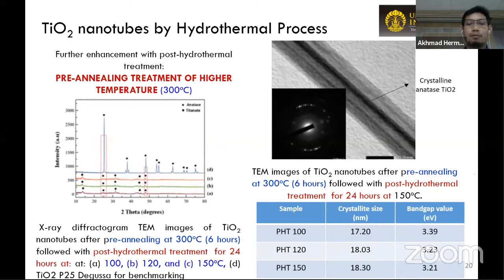From the TEM image we can see that with increasing post-hydrothermal treatment, but with the pre-annealing temperature applied previously, the nanostructure of the tube can be maintained. The nanotube is very smooth, and inside the tube there is a much darker structure. This is actually the indication of crystalline anatase. By using selected area diffraction, we can also see some dots showing that the crystallinity is improved significantly.